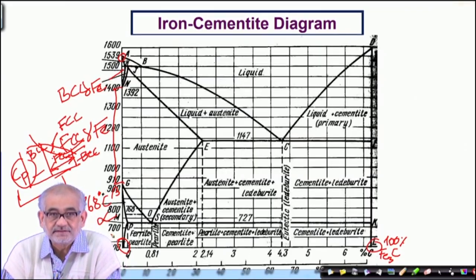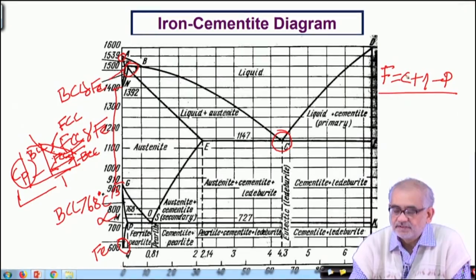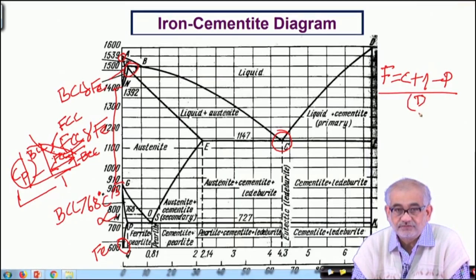This kind of crystallographic transformation of pure iron allows a large number of phase transformations to occur in steel, and because of this possibility we see very large variation of crystallographic forms and hence large variation of properties. We also see that steel will have certain invariant transformations, dictated by the Gibbs phase rule: F = C + 1 − P, where F is the degree of freedom, the +1 represents temperature only (for condensed systems where only temperature variation matters), and P is the number of phases present.